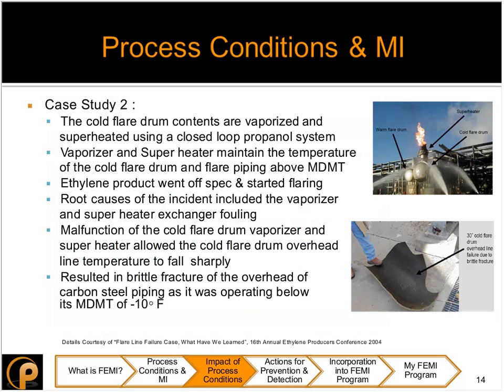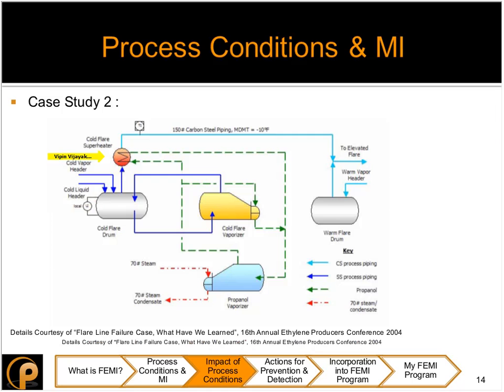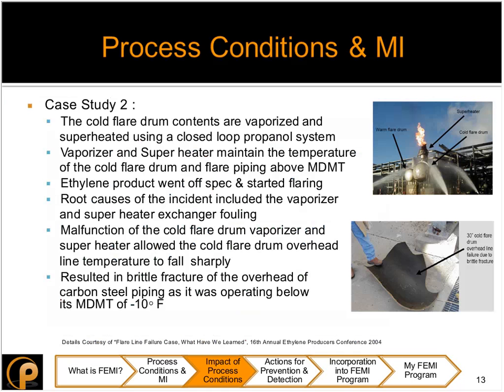Now, the failure scenario starts when the process plant produces an off-spec product at the ethylene converter, which leads to flaring of the ethylene product via the cold flare drum. Through a sequence of events, the cold flare overhead line that you can see on the previous slide, I'll just go back to it right here, is made of carbon steel and has a minimum design metal temperature of minus 10 degrees Fahrenheit. And we'll get back to the failure that happened.